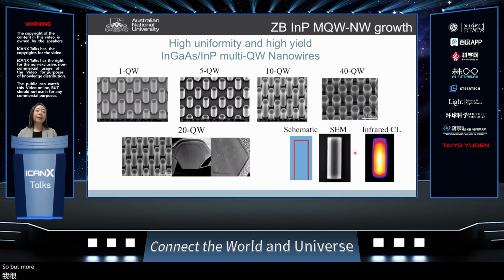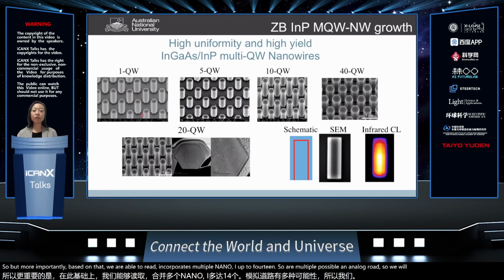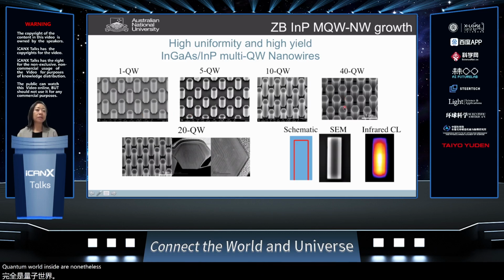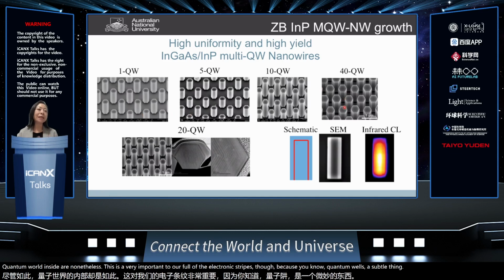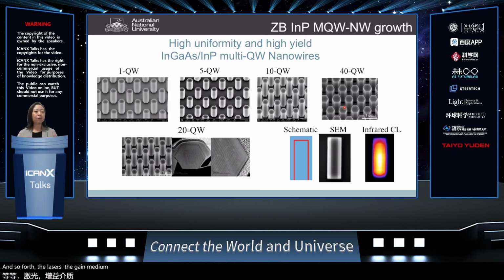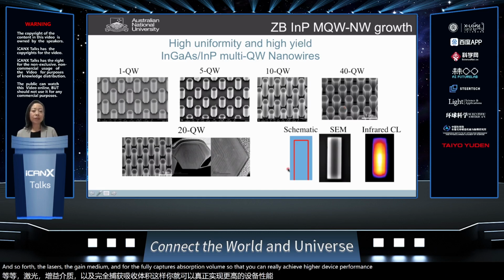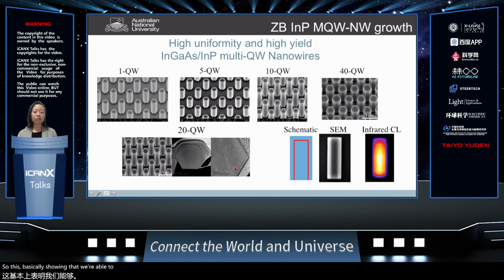But more importantly, based on that, we are able to really incorporate multiple quantum wells in nanowire growth. We have used this zinc blende-based indium phosphide nanowire, and we're able to grow up to 40 quantum wells inside our nanowire. This is very important for optoelectronics, right? Because quantum wells are so thin, you really need to build enough volume. For lasers, the gain medium, and for photodetectors, the absorption volume, so that you can really achieve higher device performance. This basically shows that we're able to grow many; this is 20 quantum wells inside a nanowire.